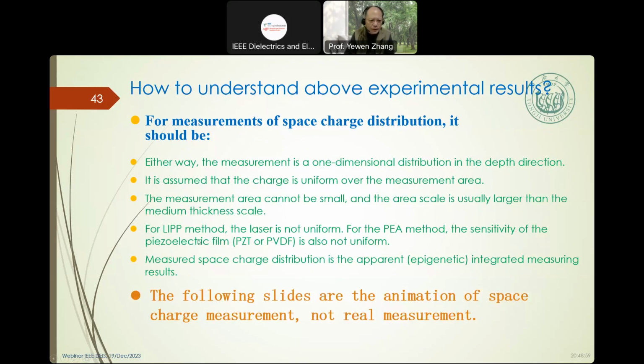thickness scale. For LIPP, for example, the laser intensity, the laser is not uniform. For the PEA method, the sensitivity of the piezoelectric film, PZT or the PVDF, is also not uniform. The measured spatial distribution is the apparent or the integrated measurement result.